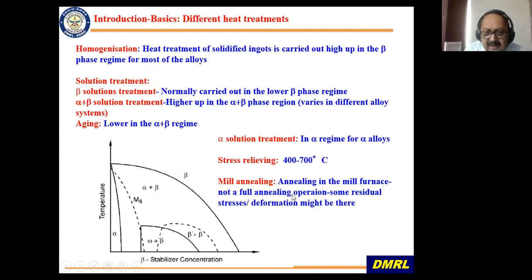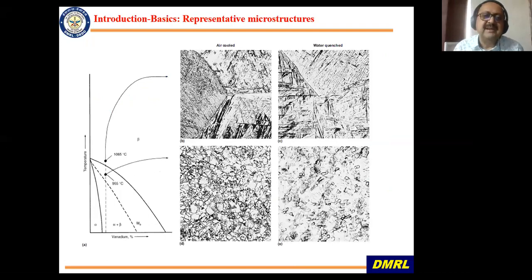And then in the case of titanium alloys, you also hear about a term called mill annealing. Now, mill annealing is when you are processing the wrought material, that is either a rod or a bar, what you do is anneal in the furnace for not very long, maybe roughly 1 hour or so, so that some annealing is done, but it is not a full annealing, mind you, and some amount of deformation still remains, and this is known as a mill annealed structure. Normal supply conditions for most of the titanium alloys are mill annealed unless you tell the supplier to provide you in certain heat treatment conditions.